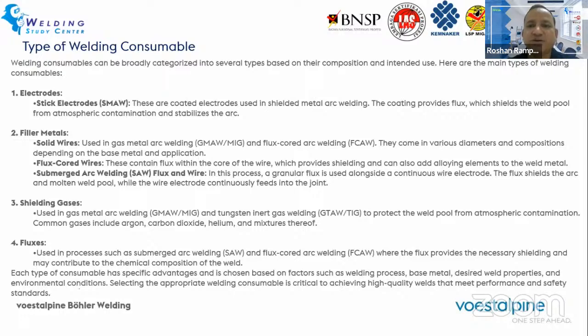So what is the main function of the coating? It contains a mixture of flux. Basic function is it helps to shield the molten weld pool from the atmospheric gases and to stabilize the arc. In some cases, it also acts as a medium to add additional alloying elements from the flux. Then for GMAW or FCAW, the wires are solid wire as well as flux cored wire. For MIG and TIG, these are solid wire. For FCW, it is a cored wire or tubular wire. Then for submerged arc, there are two components. One is the wire and the other is the flux. So they are fed separately, but in combination, they determine the properties of the deposited weld metal. So these are the welding consumables for different processes.